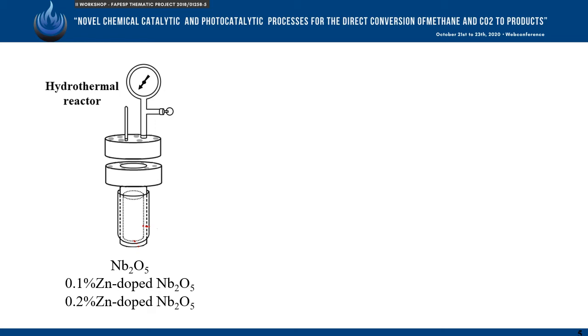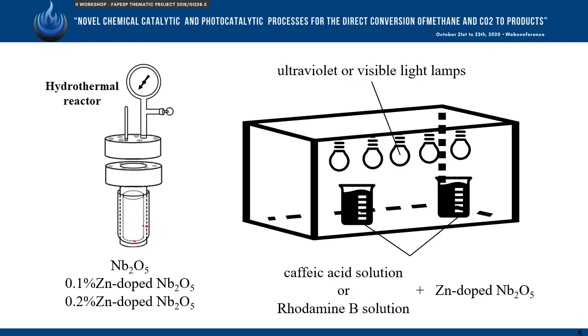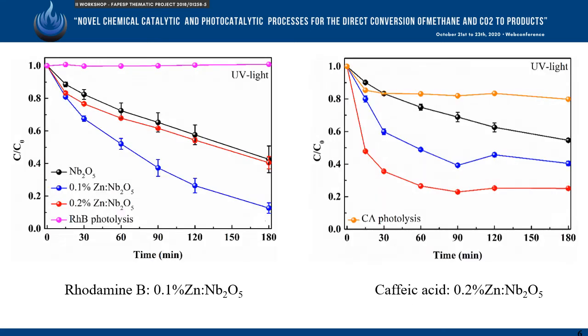The photocatalytic activities of the samples were evaluated for the photodegradation of rhodamine B and caffeic acid. In a typical procedure, 10 mg of the photocatalysts were added into the rhodamine B or caffeic acid aqueous solution. These dispersions were exposed to ultraviolet and visible radiation. The best photocatalyst for the degradation of rhodamine B was the sample containing 0.1% of zinc, degrading approximately 90% of this compound under ultraviolet radiation.